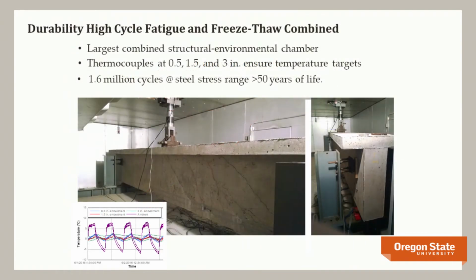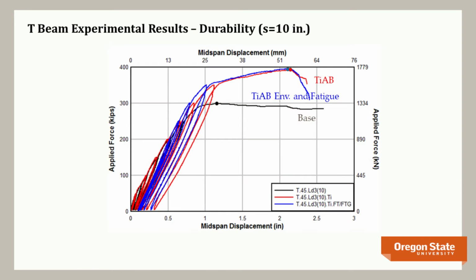Again, we do the same thing in terms of our freeze thaw and fatigue. And then we test them. Control specimen shown in black. Red is if I just test it without the durability. Blue is including the high cycle fatigue and freeze thaw. And again, we get almost the exact same answer, even though we did a heck of a lot more work with the fatigue and the freeze thaw. So no environmental deterioration. Here's our first application of it.